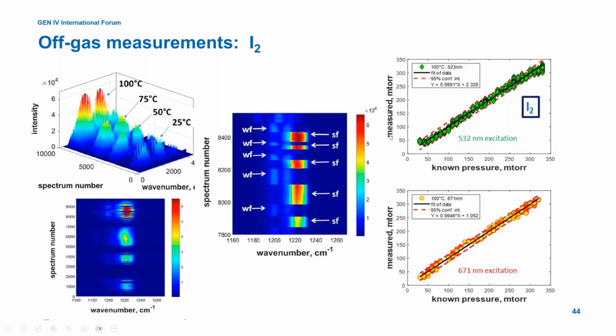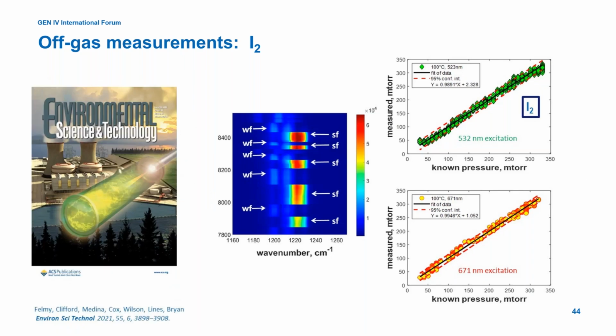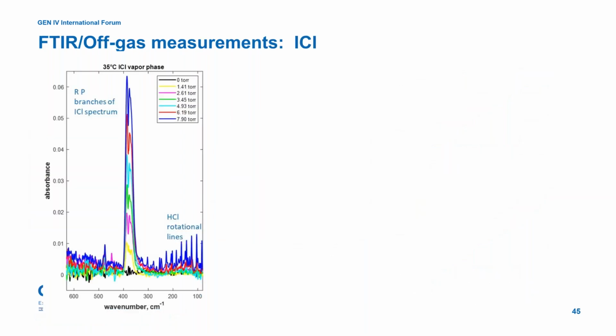When we use that, we can measure with our probe the concentration of I2 in the gas phase compared to the known pressure. Again, nice one-to-one parity plot with both the 532 nanometer excitation. We've also used the red laser system for 671 nanometer excitation as well. Get really nice measurements with that. And this was summarized in the journal article Environmental Science Technology that was published just a couple of years ago. The next application is measuring ICl gas.